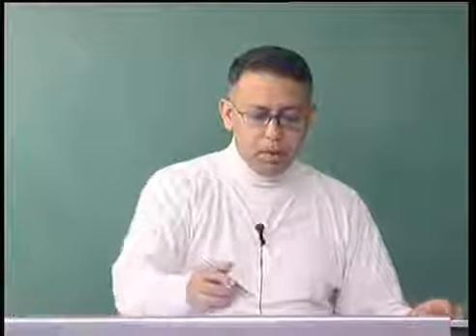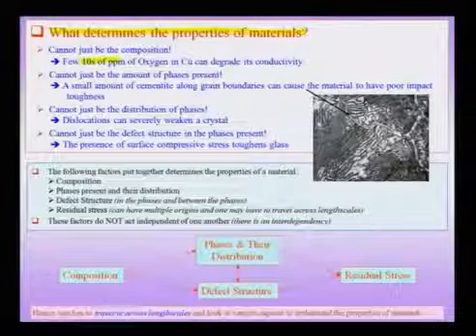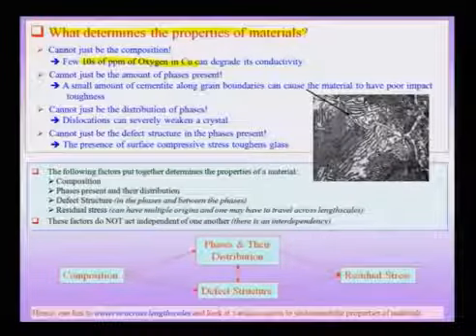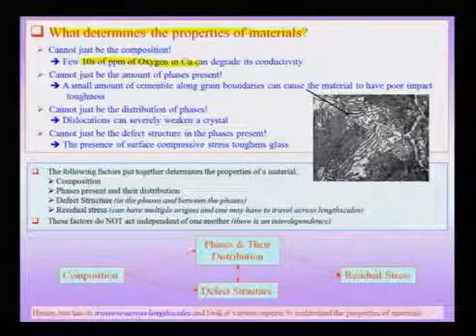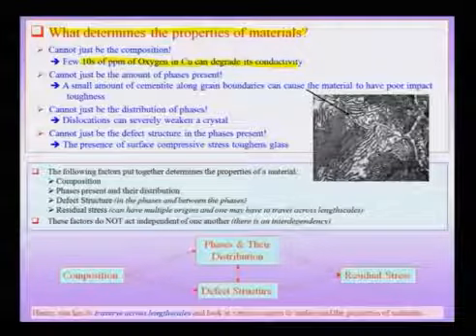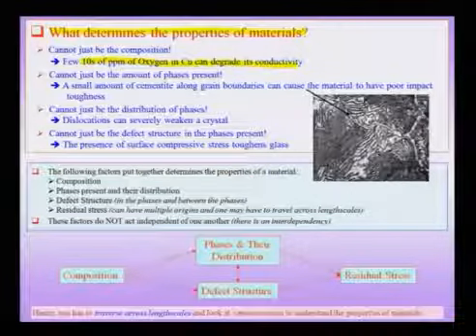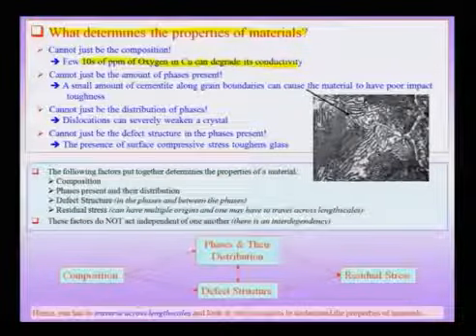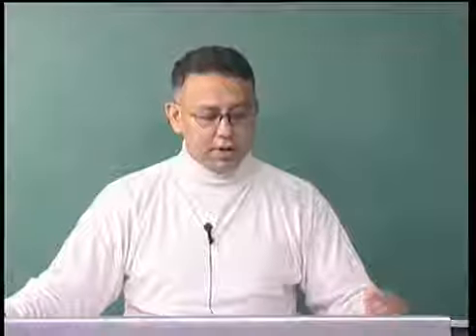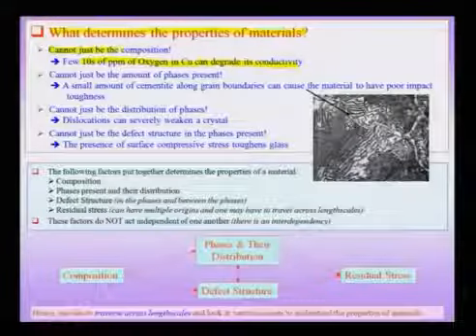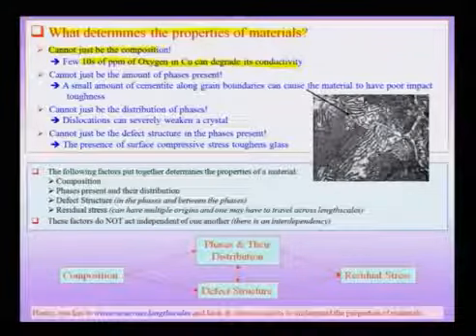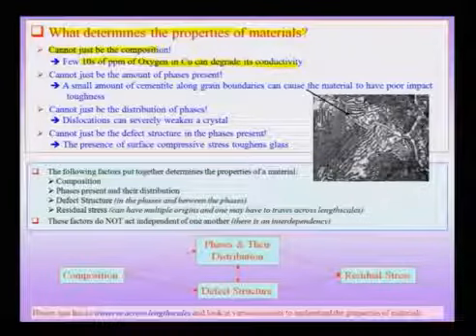Okay. The first thing we see is that if I put in a few tens of ppm of oxygen in copper, this would degrade its conductivity drastically. Therefore, I need to go in for what is called oxygen free high conductivity copper to make my copper wires, which is used for electrical conduction. Therefore, just knowing the composition cannot give me my properties. I need to consider further factors.